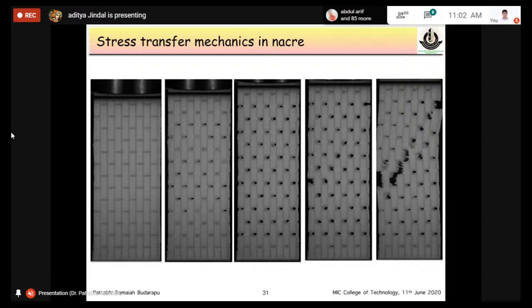So they actually slide a lot before the composite is actually failed. Because of the sliding, there'll be crack initiations, many crack initiations, and then they continue to grow significantly until the material fails. So these pictures indicate the image captured at different stages before the failure.